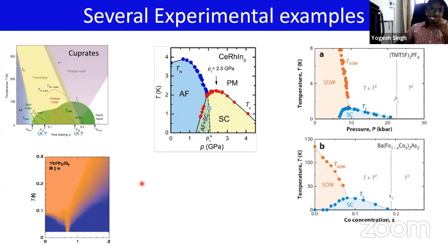So these kinds of phase diagrams, which I showed schematically, seem to be ubiquitous in strongly correlated materials. This is a phase diagram of a particular cuprate. And you can see that when the magnetic order is suppressed by doping, you find all kinds of interesting phases. The possibility of a quantum critical point hiding here is still being debated, but the point is that up to hundreds of kelvins, there is strange behavior in the metallic state above TC.